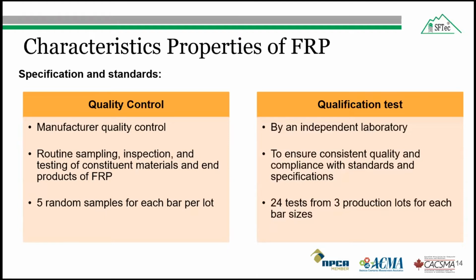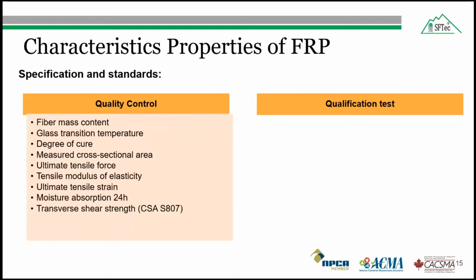Like for SFTec, the University of Sherbrooke is doing the qualification test. The qualification tests are conducted to ensure consistent quality and compliance with the standards and specification. A total of 24 tests from 3 production lots of each bar size should be tested. From one production lot, there will be 8 samples, and these are the recommendations of CSA S807 and ASTM D7957. The following properties should be determined for quality control.